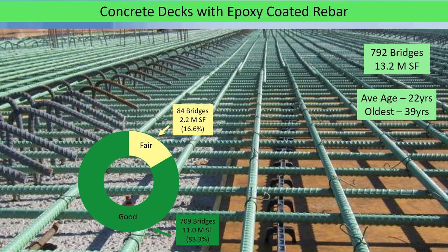So again, the epoxy coated rebar decks are doing pretty good. Most of them are in good shape. 84 of them are in fair. In the 1980 to 84 and early in the 1980s as a whole, the epoxy coating looked different than what we have today. They tried some different coatings, black and brown, and they weren't as thick as we have them on today. So those early generation epoxy coatings may start seeing some problems.